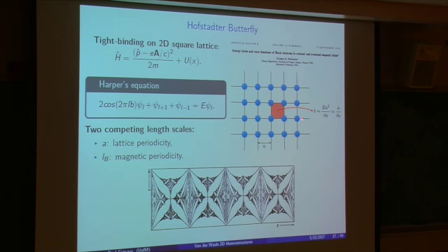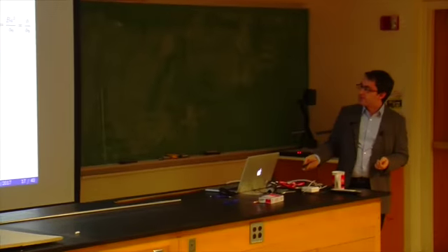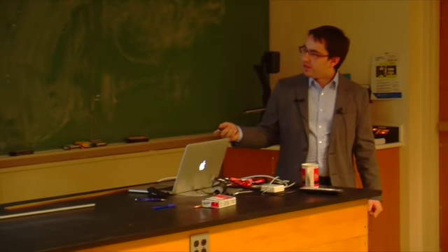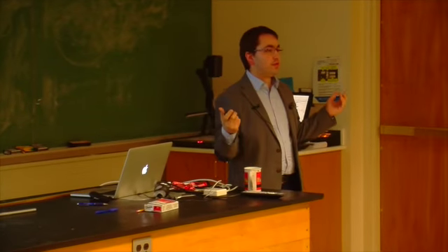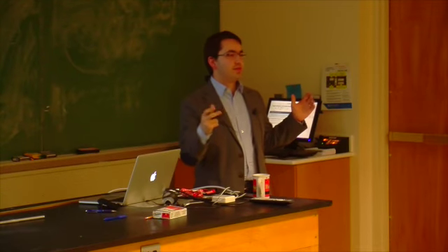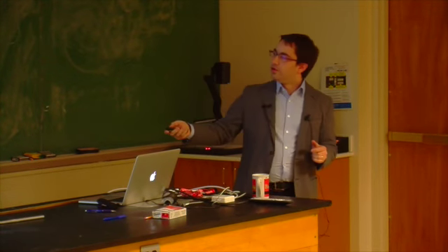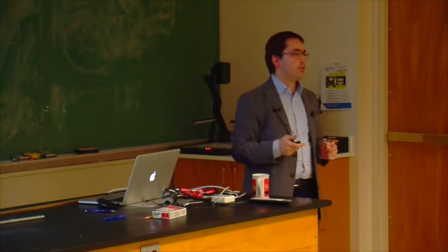The problem is that to reach integer values, or values that are not too small, of this parameter b, if you want the periodicity here to be the periodicity of an atomic lattice, you would need absolutely gigantic magnetic fields, something which is not realizable in practice. And so this was long just a dream, because we could not have periodicities that are large enough to really probe this kind of pattern.